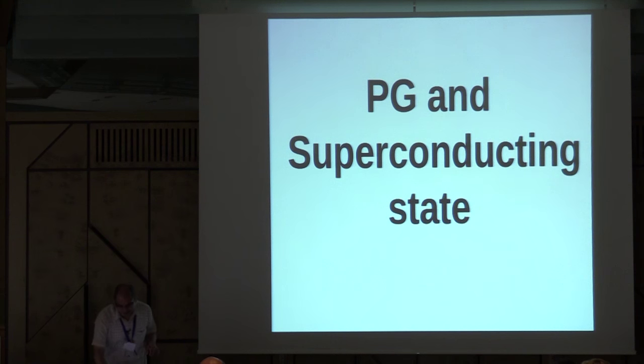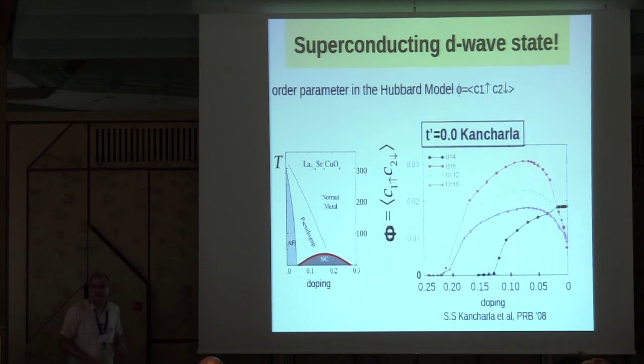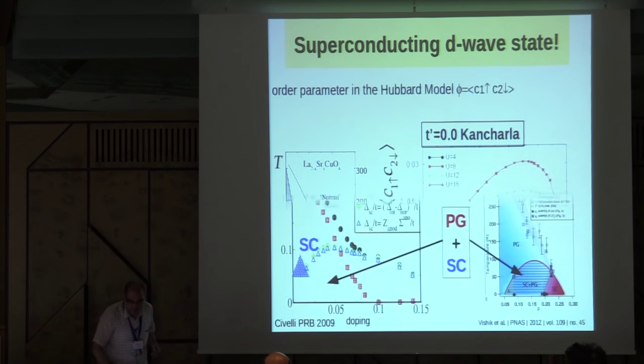I'll come back. The last thing I want to say is about the superconducting state. Of course, with cluster DMFT, we have studied the superconducting states already in early times. And what you see, in fact, is a superconducting dome, which is a function of the interaction parameter U. This is U in units of the bandwidth. You see, it has a dome-like shape. Around half bandwidth it is also maximal, and then decreases for increasing U. It seems like J, the antiferromagnetic coupling, which scales like 1 over U, could be related to this strength of superconductivity.